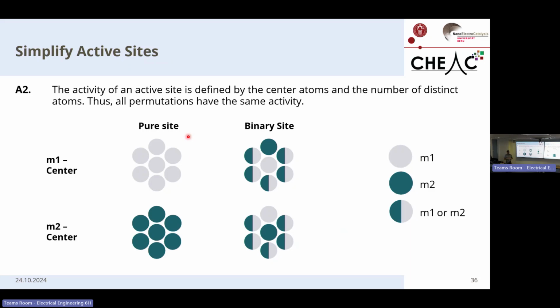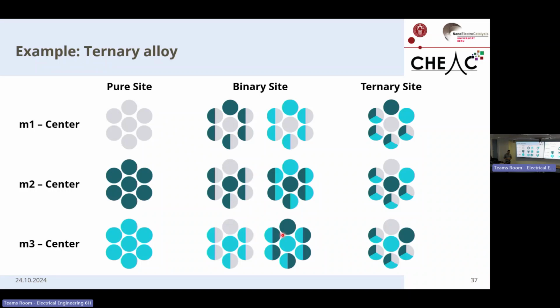And let's group active sites based on their complexity. And the way we now group them is we define the active sites as similar in activity by their center atom and the number of distinct atoms in the surrounding. So a binary alloy we can describe now using 4 types of active sites. We have the pure sites and we have the binary sites. Moving on to an example of a ternary alloy, we now have 9 types of active sites. We have the 3 pure sites, we have 3 types of binary sites and 3 types of ternary sites. And the same thing we can do for all other alloys.